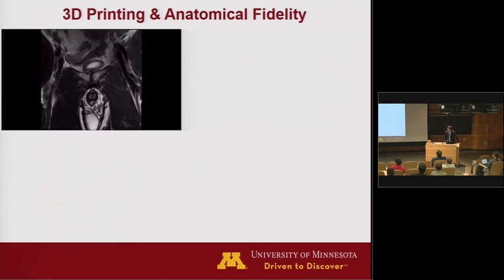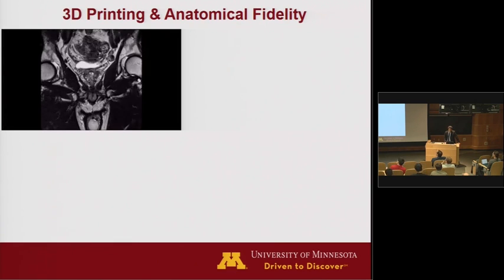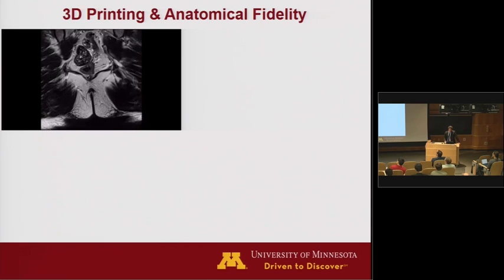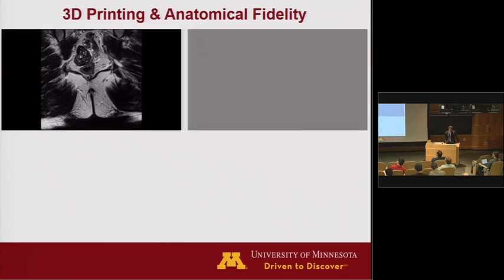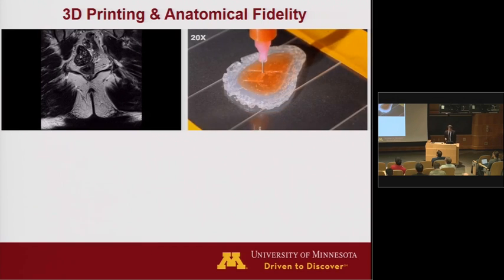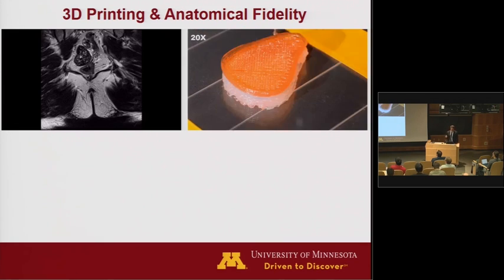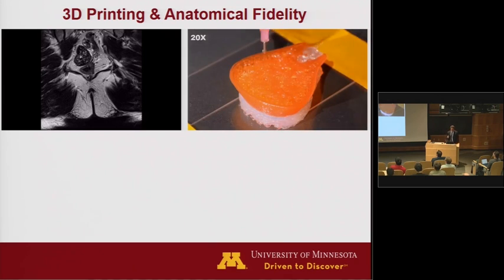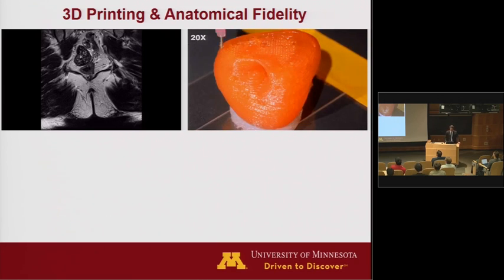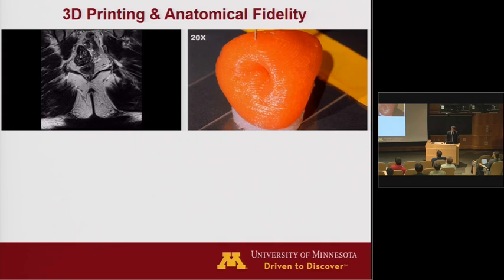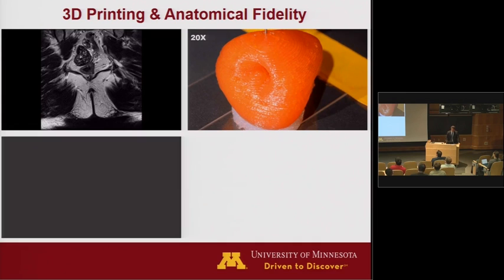So first of all, we did find a patient. We got an MRI scan from the patient in order to figure out the anatomical structure of these models. We then 3D printed these models using our custom 3D printing platform. So these are inks that we developed in our lab, which in principle should have much lower Young's moduli than the commercial inks. And so this is a soft ink printed in the form of this prostate here. And there's also a sacrificial ink there too, that's the white that we cut away later on.